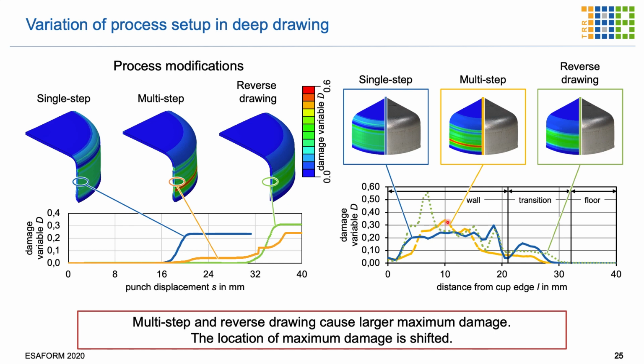So this is the maximum damage in the wall at this point. However, if you use the reverse one, you get the maximum damage at another position in the wall, and if you use the single step process, you get the maximum damage at another position, and more important, in the transition part where you have critical loadings of the part, you see that the single step process delivers the worst damage compared to the two others.